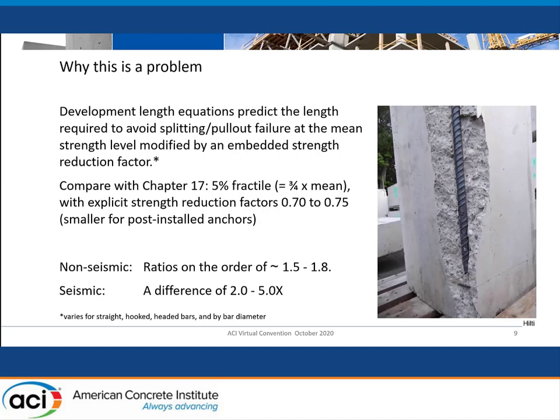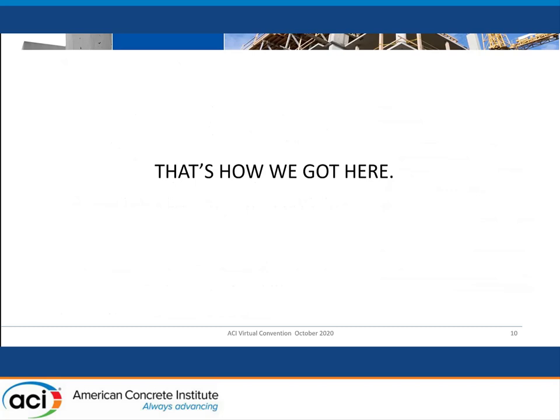The photograph I'm showing here is a result of a PRISM test that we do when qualifying post-installed reinforcing bar systems. Along with qualification of the post-installed bar, we run a parallel test with cast-in-place bars to show that for that concrete and specimen, you get roughly the same behavior in terms of shear lag. We run these tests at 35D with number 8 bars, giving us a nice window into how number 8 bars at minimum edge distance with very little confining steel behave in terms of development length. What we find is those bars reach nominal yield — they get to 60 KSI — but rarely do they get anywhere near the stress level you would need to call them yielded, which would be about 75 KSI.